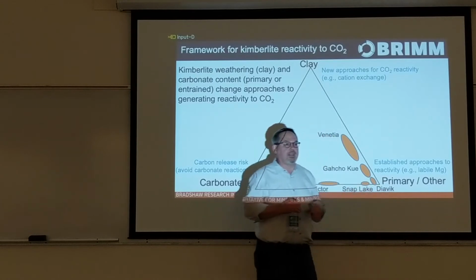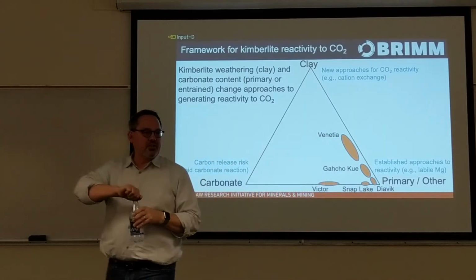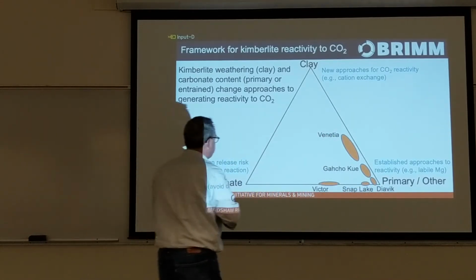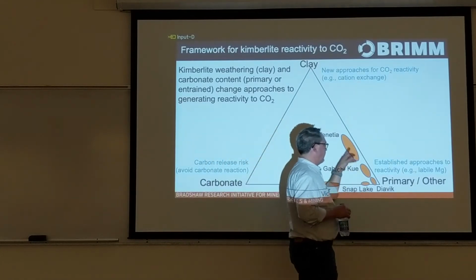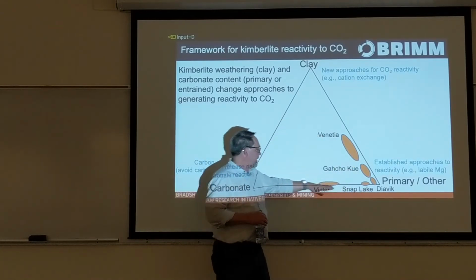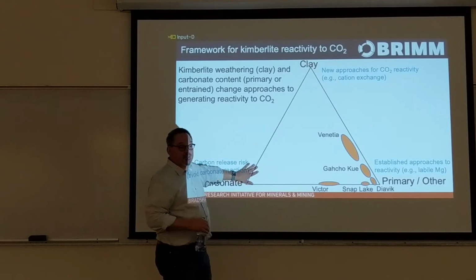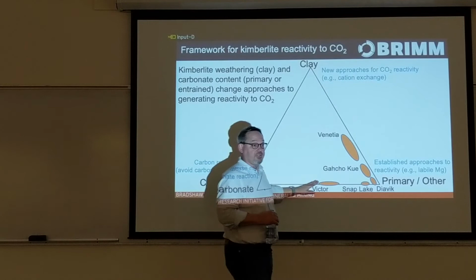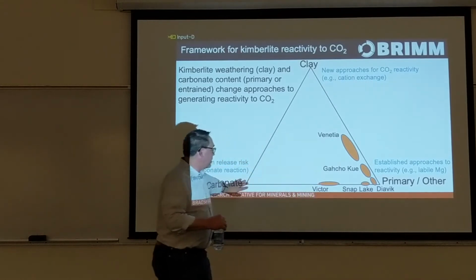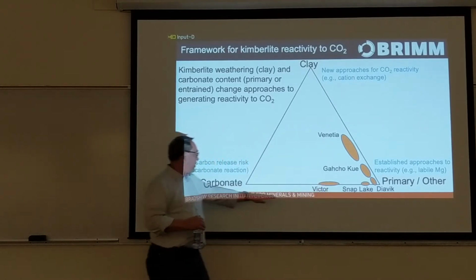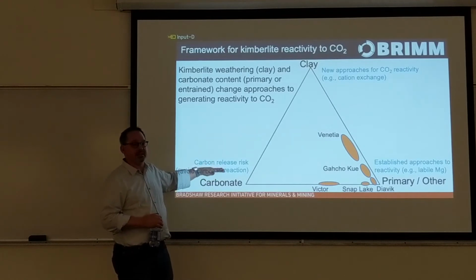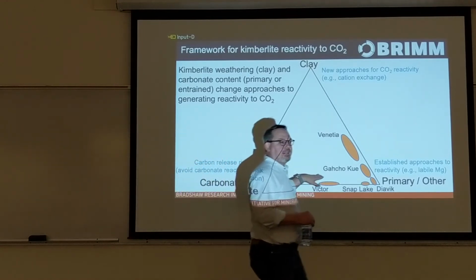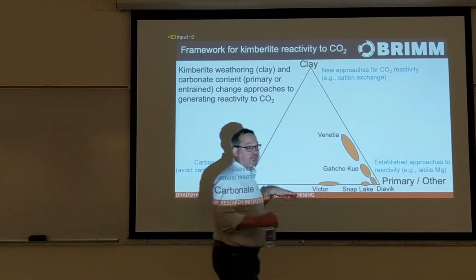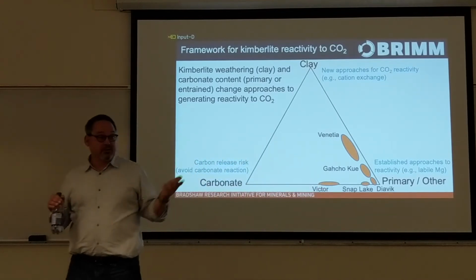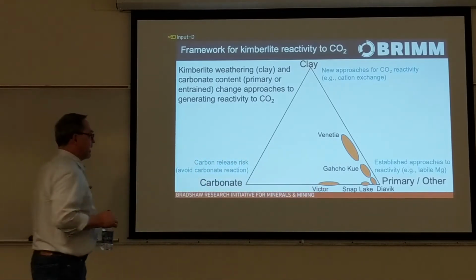And that was kind of like a nickel mine from our perspective. It was serpentine rich and it was reactive and all was good. And then we started looking at Victor and Snap Lake and Venetia. And there's Victor, there's 30% dilution by sedimentary carbonate rocks. There's Victor in their tailings. You can see that in the tables. So you've got a very, very large CO2 release risk if you start messing with those tailings, because a third of your tailings are carbonate minerals. And if they release the CO2 that's bound to the calcite, it's going to be really hard to overcome that.